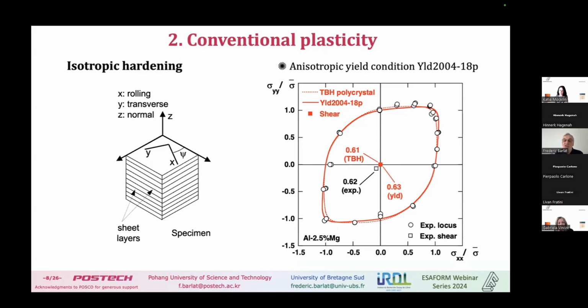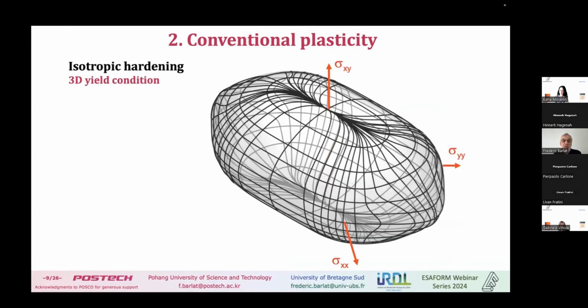And you see, of course, there's a fit with all those experimental data, but for the continuum model, it's fitted with the data, but the Taylor, Bishop, and Hill, the crystal plasticity model, is done with the texture. But you see that all those 3 approaches, experiments, crystal plasticity, and the constitutive model, 2004, they are all giving something like a rugby ball. Okay, it's not like an ellipse, like a Hill. And of course, we need to do that in 3D.